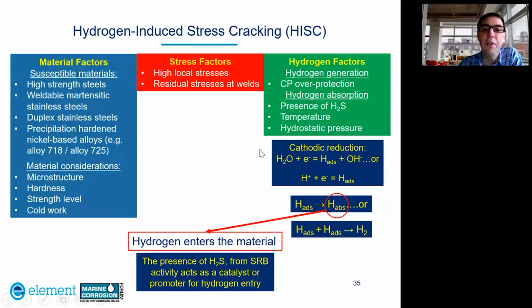So at the cathode, the material we're protecting, either the steel or the duplex stainless steel, we get the cathodic reduction reaction, which can be the reduction of water to form hydrogen and hydroxide, or the reduction of hydrogen ions in the solution to form hydrogen atoms. So these hydrogen atoms, which are adsorbed onto the surface of the metal, can then be absorbed into the metal, or they can recombine on the surface to form hydrogen gas that will then bubble off the surface. So the result of this reaction is that hydrogen can then enter the material.